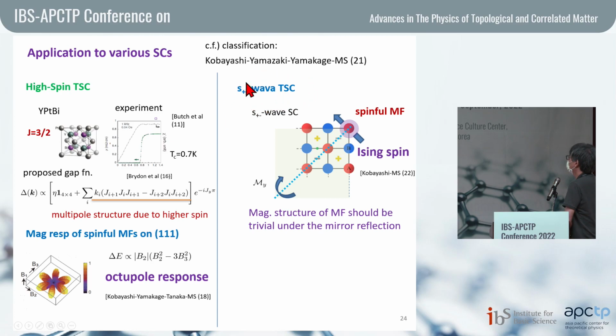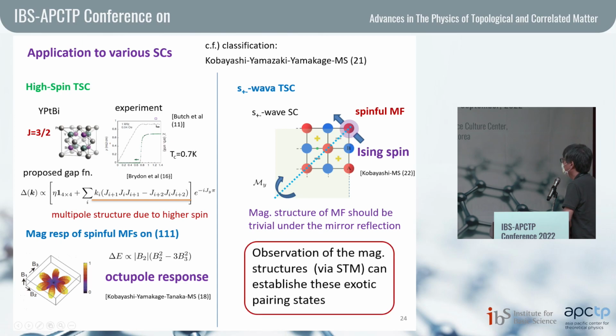And here I show another example, S plus minus wave topological superconductors. As I mentioned before, this system supports the Majorana corner mode protected by the mirror reflection symmetries. So this means that the magnetic structure of the Majorana fermion should be trivial under the mirror reflection symmetry, since we are considering the trivial representation under the mirror reflection symmetries. And we also know that this should be odd under the time reversal symmetries. So this means that the consistent magnetic spin structure should be the eigenspin in these directions. If you can detect this kind of structure by using STM measurement, then we can directly have evidence of the Majorana fermion protected by the mirror reflection symmetries. So anyway, the observation of the magnetic structure via STM can establish this exotic pairing state.